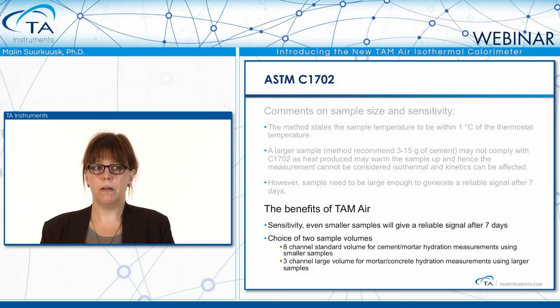So the benefit of TAM Air in this case is that TAM Air has a high sensitivity. Even smaller samples will give a reliable signal after 7 days. And with the choice of 2 sample volumes, 125 or 20 milliliter, you can optimize depending on the sample which type of calorimeter you are going to use. The 8-channel standard volume calorimeter is perfect for the cement or mortar hydration measurements. Then you can utilize smaller samples. If you have concrete samples, the 3-channel calorimeter is a better choice, where you can use bigger samples to get whatever aggregates you have in the cement also and get a more representative sample.